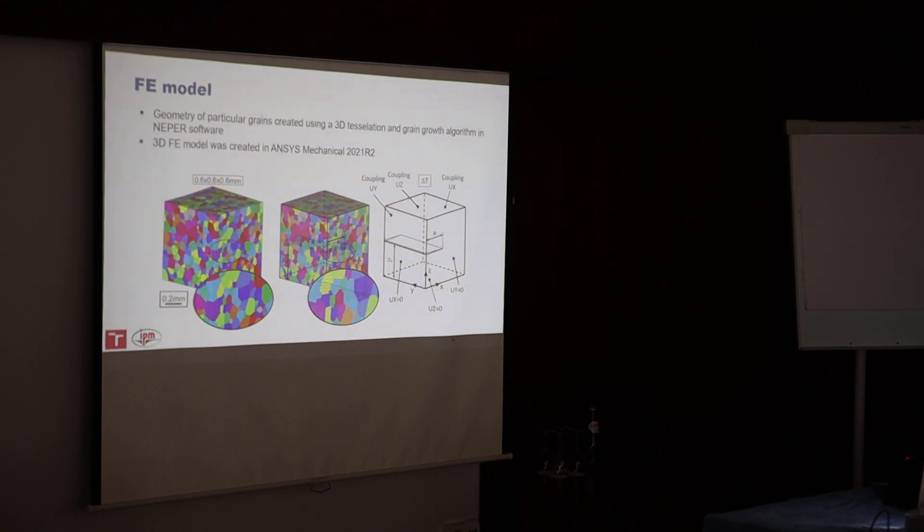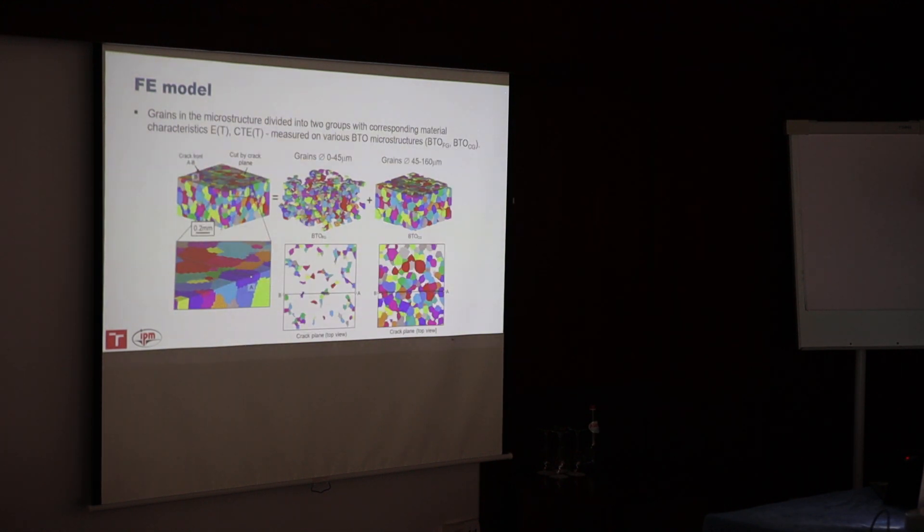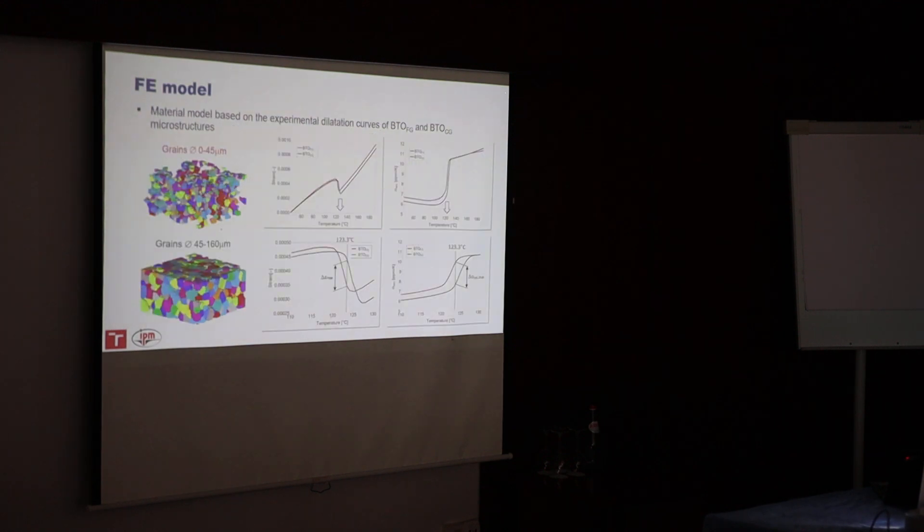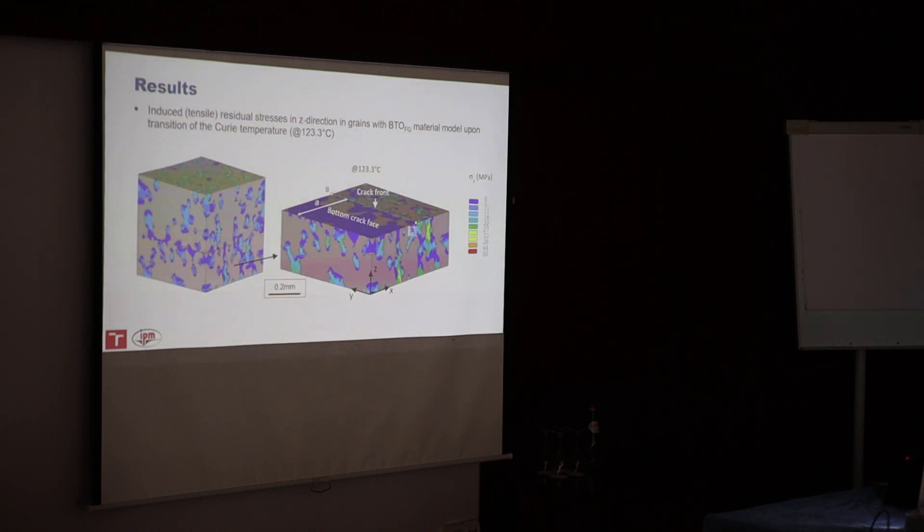We then transformed this geometry into finite element system ANSYS where we created the finite element mesh. We also inserted a crack in various vertical positions and also of various crack lengths in order to calculate the stress intensity factor along the crack front. We divided the microstructure into two groups of grains: small grains 0 to 45 microns and then the big grains. To these two groups we prescribed corresponding material characteristics measured on the fine and coarse grain microstructure, and then we performed thermal simulation.